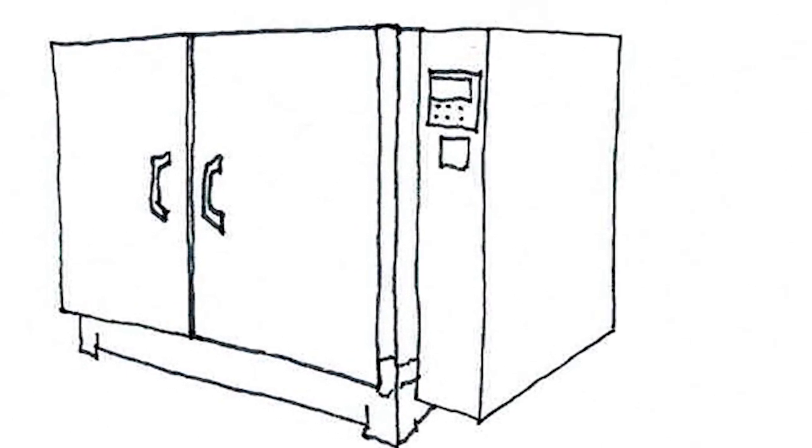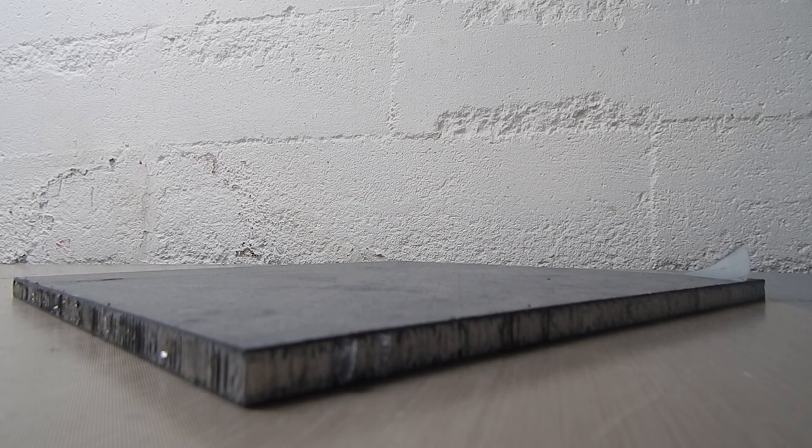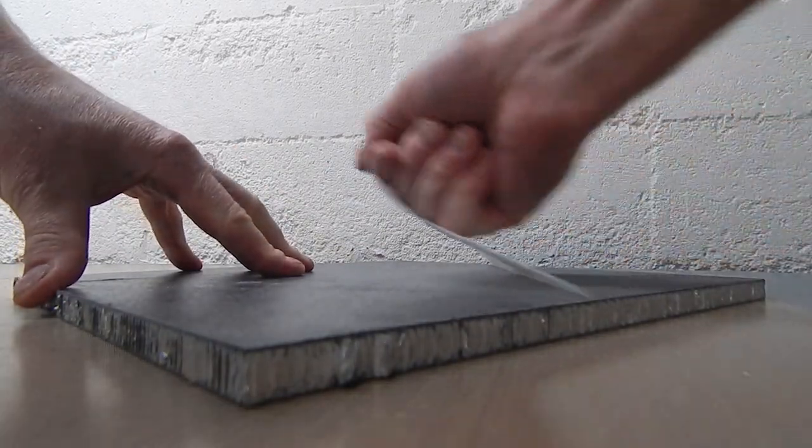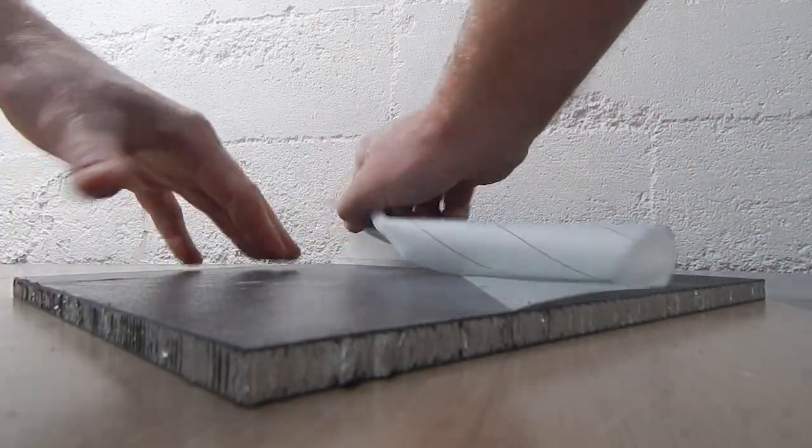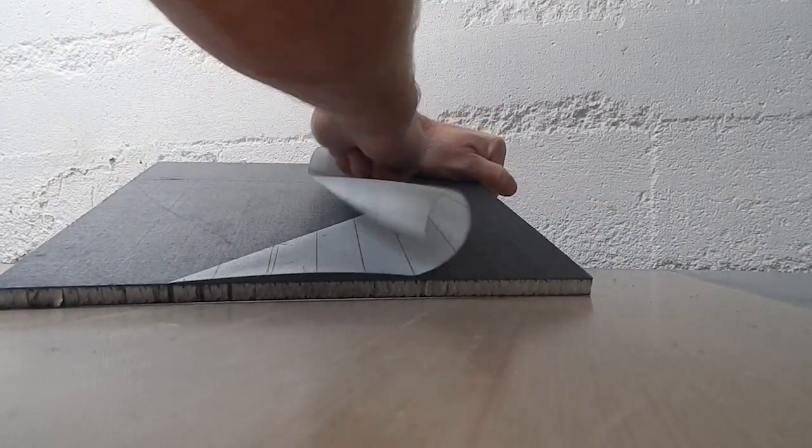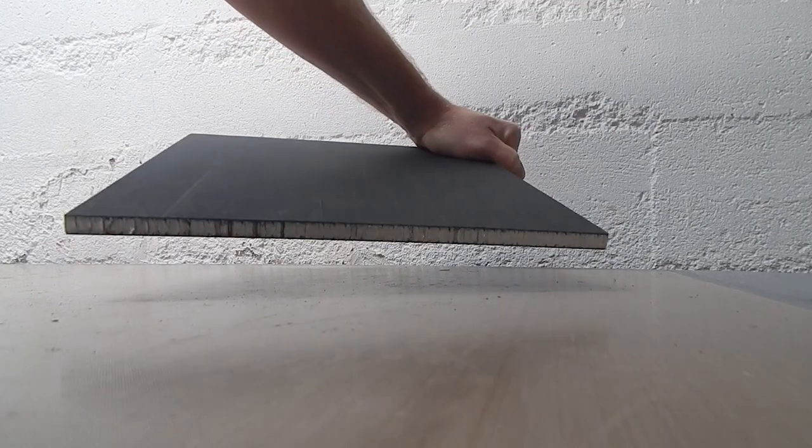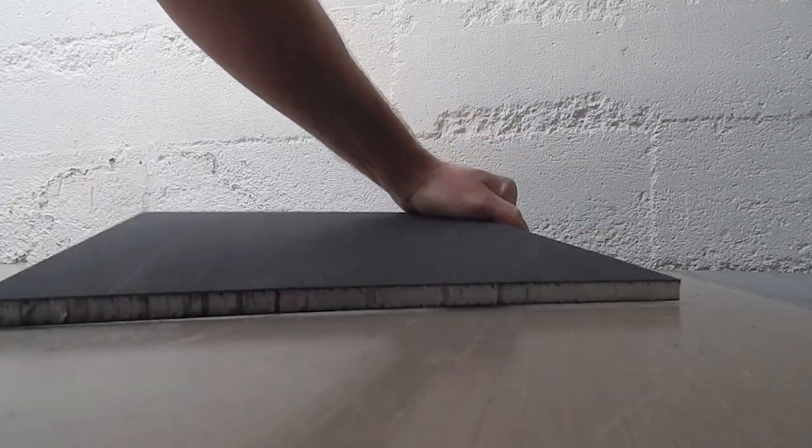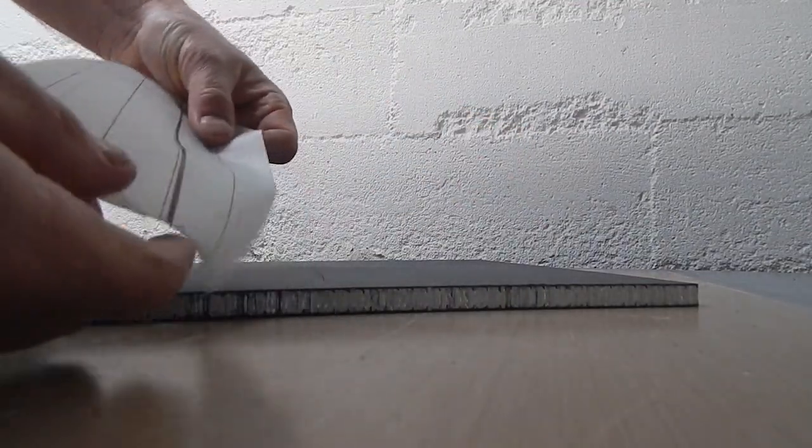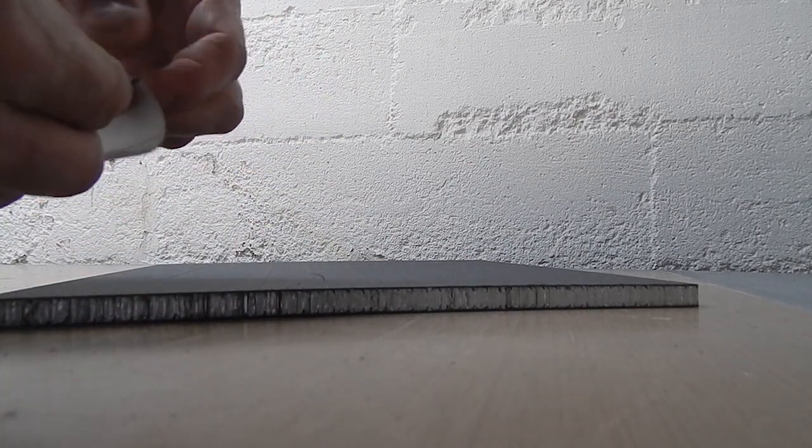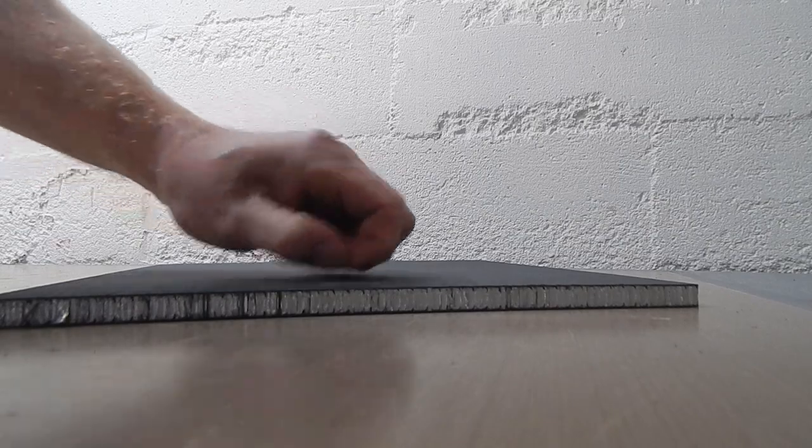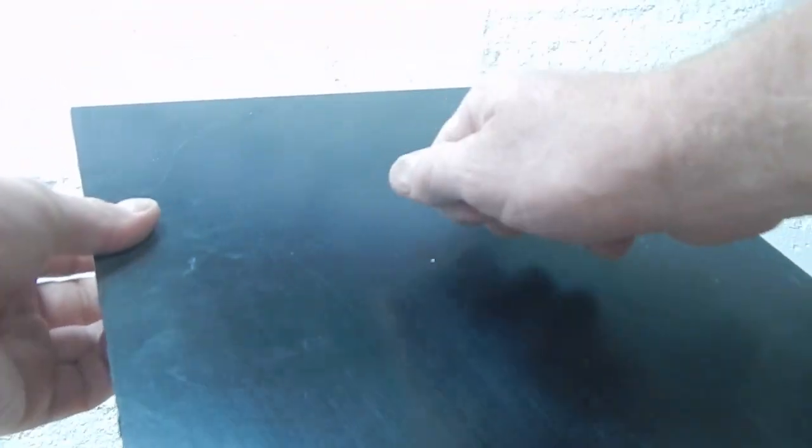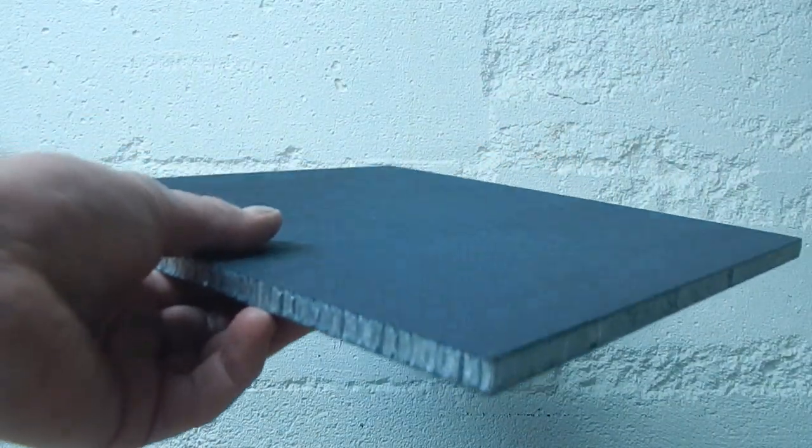But here it is, demolded, trimmed, pulling the peel ply off. The peel ply did not look great. I think that it had seen better days and probably didn't add anything. And I wasn't super careful pulling it off and pulled off a piece of the uni because there's no woven to protect it. You can really easily grab a strip and just yank it up. And there it is, stuck to the peel ply. You can see where it came off. It's one of the hazards of working with unidirectional right on the surface. But it looked really nice.